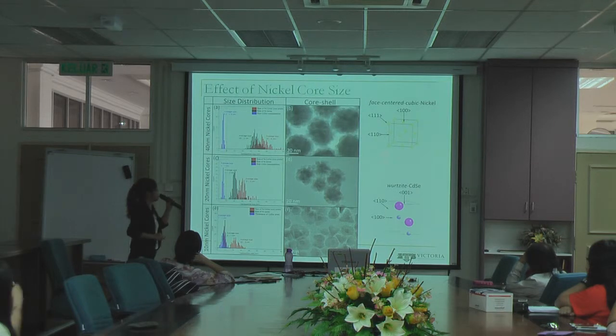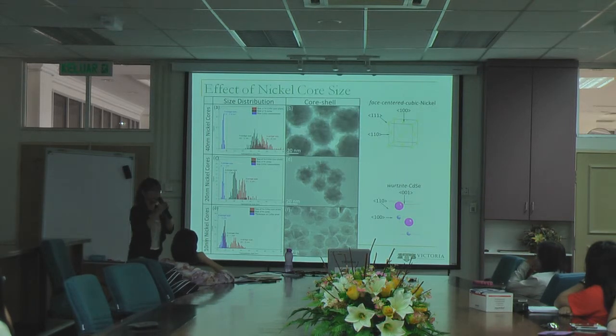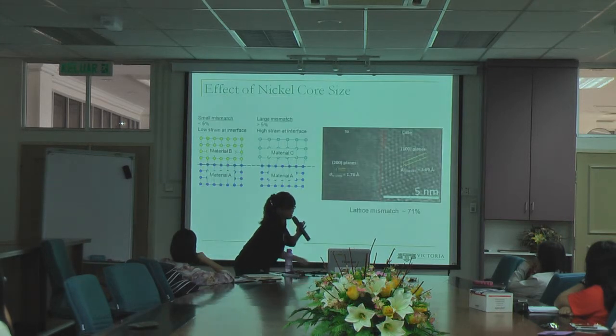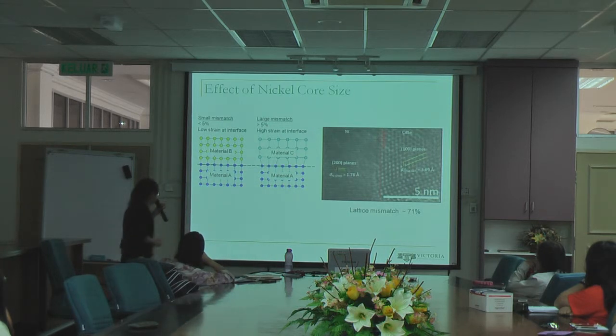For example, nickel is made up of a face-centered cubic crystal structure, and cadmium selenide mainly forms the hexagonal wurtzite structure. These two structures are very different from each other. So when these two materials are in close contact, we can imagine that the strain energy at the interface will be very high, making it not favorable to have the interface. To go into a bit more detail on that, we can have a look at these two diagrams. So for example, the first pair of materials are a pair with very similar crystal structures.